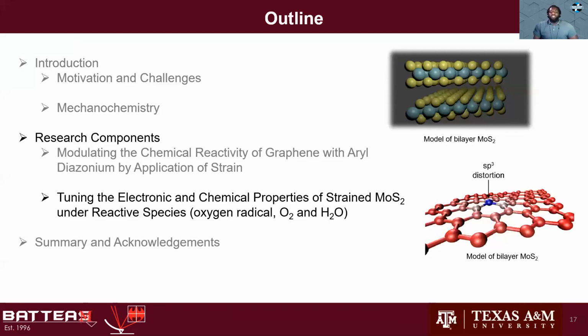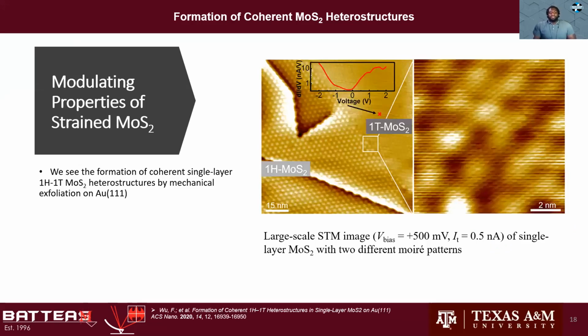Next, let's explore ongoing work studying strain and its effect on the reactivity of MoS2 in the presence of environmental reactive species. And so in our lab, Dr. Fenglu Wu developed a mechanical exfoliation technique that allows for the transfer of single layer MoS2 onto the surface of gold 111. Through characterization, it was seen that a coherent heterostructure of monolayer MoS2 was intact. The 1H and 1T phases were coherently shown on the gold 111 surface.